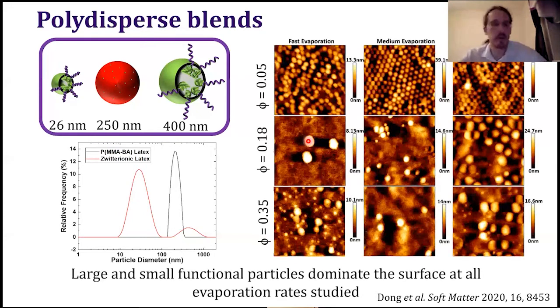We had these green particles, which have a certain anti-biofouling component on the surface. And then the red line is their particle size. So we have a very broad particle size, below and over our normal latex particles, which are here, and they're a bit less polydispersed. But overall, it's a polydispersed blend. And we have very small and very large particles, which are the functional particles that we want at the top. So if we make films out of this, changing the evaporation rate and how much of the functional particles we add,